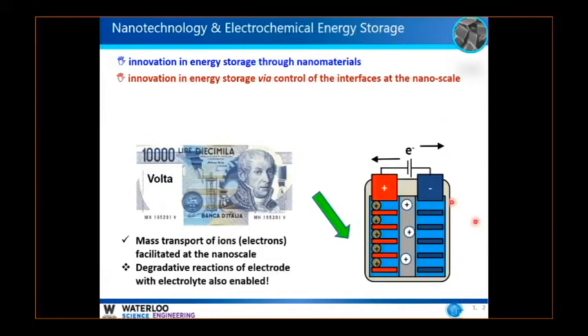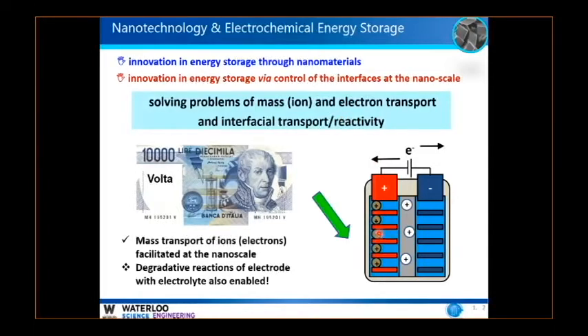So this is a positive and negative electrode. The electrolyte is this gray material in between in which the ions are carried, and electrons are forced through the external circuit, in either direction, depending whether this is going into charge or discharge. And so we have mass transport issues within both electrodes, moving these ions and electrons around. And we also have issues with reactivity at the interfaces, which are either very high positive potential or very low negative potential. And that causes the electrolyte, to a certain extent at least, to degrade and form these interfacial layers, which can really impede the battery.